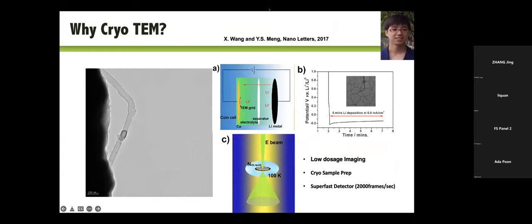The second important breakthrough we had in the Battery 500 consortium is to use cryo-TEM to look at lithium metal at atomic level so that we can study the SEI in detail. This video shows you that if it's electrochemically deposited lithium at room temperature, if you don't do anything, the lithium metal whisker is changing. That is not because the lithium metal cannot be imaged in the TEM. It's because this electrochemically deposited lithium was covered completely by SEI.